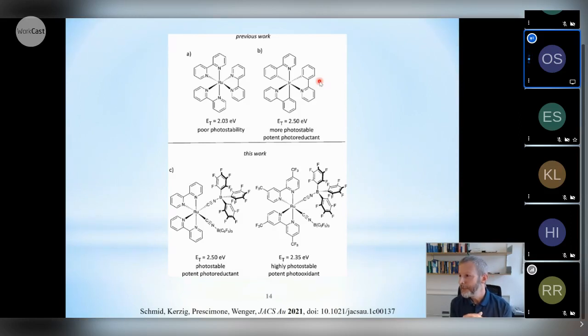So there is a guideline. You can say that the higher the triplet energy, the greater the possible substrate scope that you can possibly activate with your sensitizer. And as I said, cyclometalated iridium complexes have fairly high triplet energies, whereas ruthenium diimine compounds typically have significantly lower triplet energies and they're less directly applicable, perhaps, to triplet energy transfer catalysis.